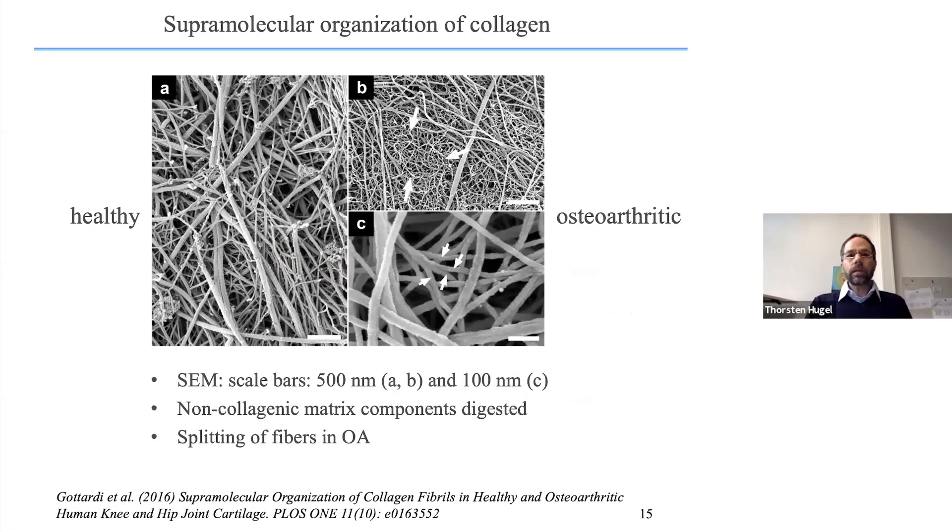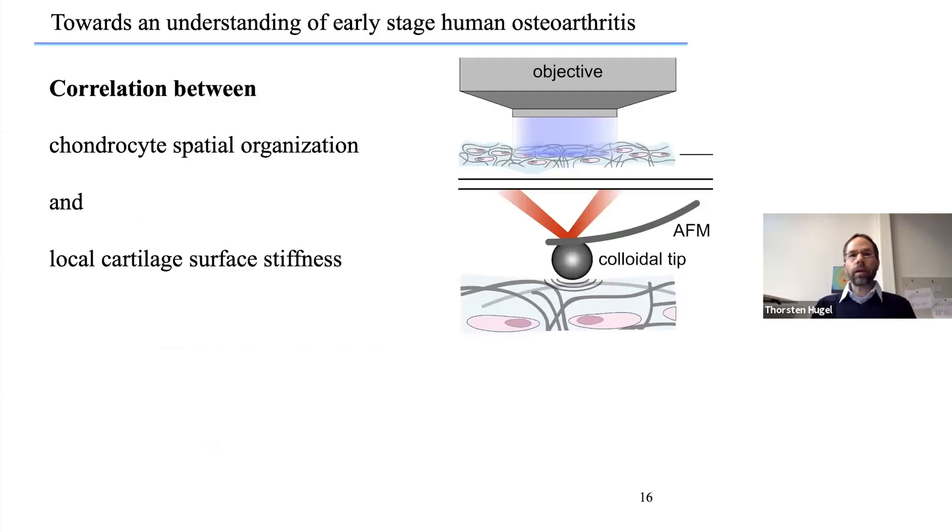This is consistent with a prior scanning electron microscopy study showing that thick fibers transition into thinner fibers in diseased cartilage. The idea was that thick fibers simply split into thinner ones. However, I find this hard to believe, because you can see one fiber appearing to thread through another—one branch going on top and one going underneath an adjacent fiber. This does not make physical sense, so I think we still do not fully understand the story, though we now have more hints.